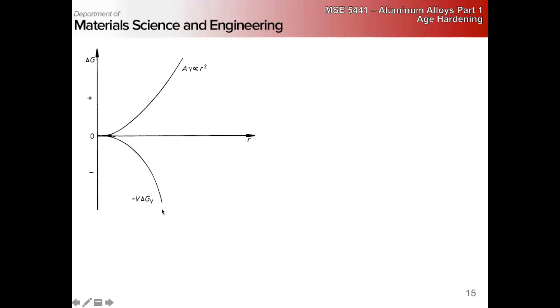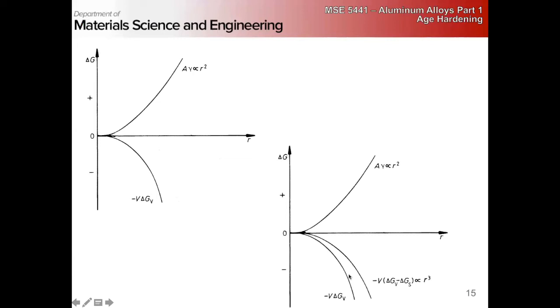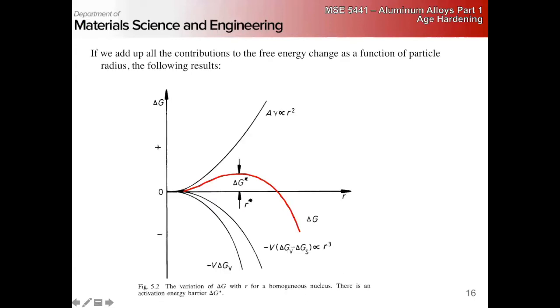right? Our volume term is negative, right? Because in this case, we're trying to nucleate the thermodynamically stable phase, right? And our strain term is going to shift that over, right? And if we add the contribution of this line and this line, we have a curve that looks like this. So what it tells us is that nucleating small particles gives us an increase in the free energy. Big particle, because for these small particles, the surface energy term dominates. For big particles, the volumetric term dominates.